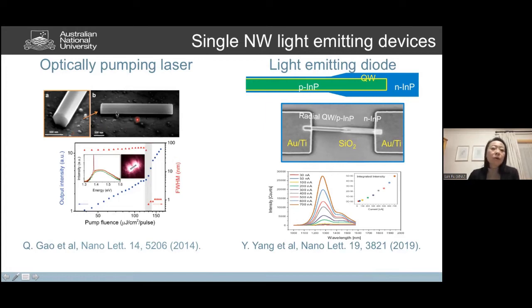This is basically because nanowires have this nice geometry. If you knock them down, the end facet is actually quite sharp. They can form quite a nice Fabry-Perot cavity in the single nanowire. If you do optical pumping, you can see lasing from that. That's really a nice demonstration of the good material quality coming from the epitaxial growth.